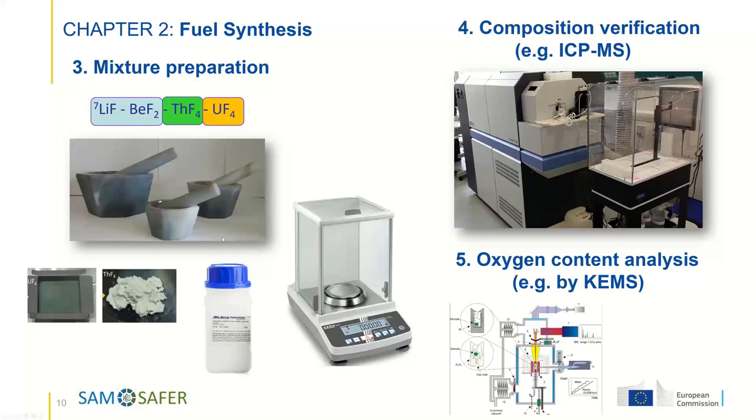Okay, so then we mix. Then we make the mixture preparation of the dedicated salt, and then we verify the composition again with ICP-MS, but not for chemical impurities, but for the ratios of the matrix and fuel components. So this is done again by ICP-MS.